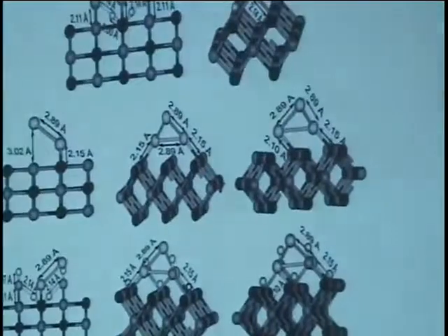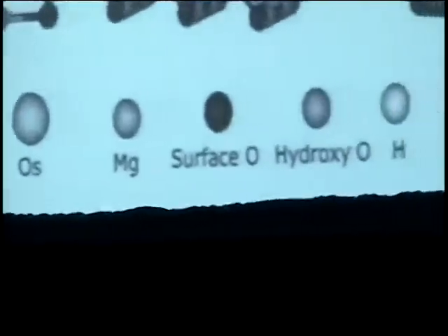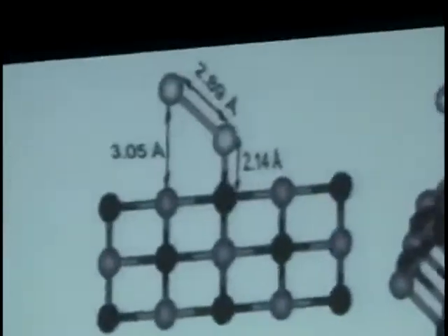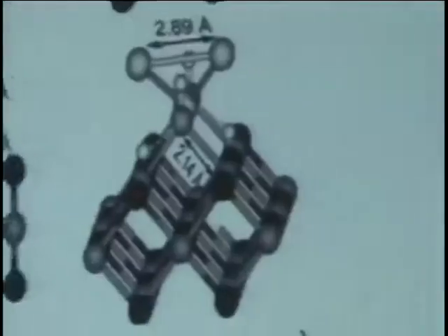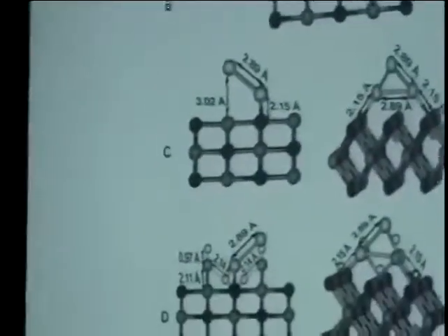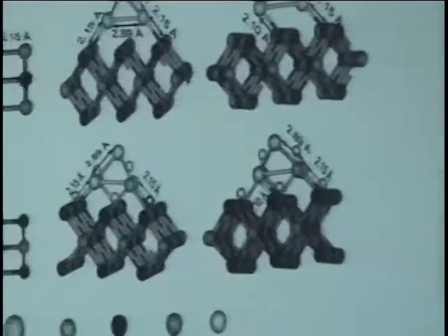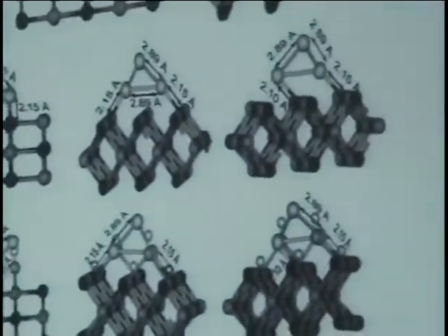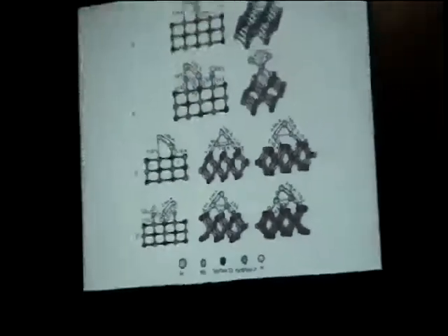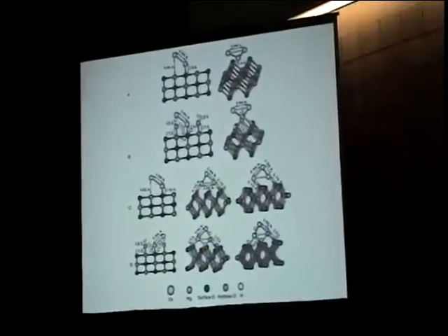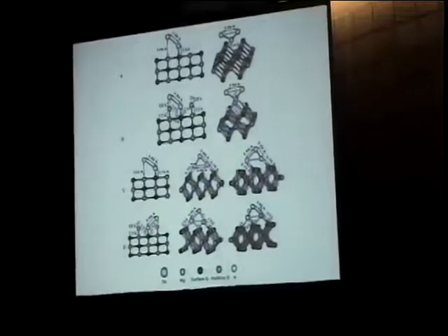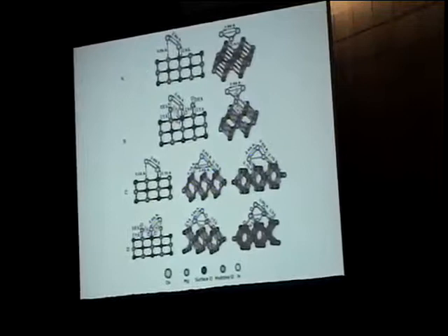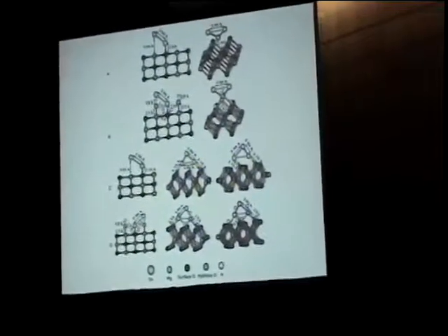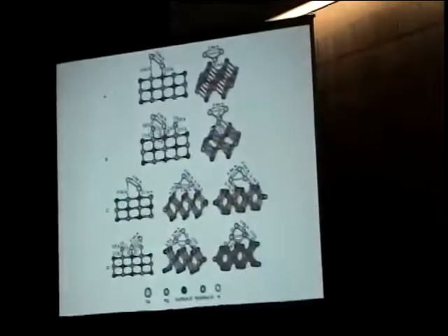So the structural models, the student did all the geometry. Thank goodness the student did it and I didn't. Figured with this face of MgO, with it hydroxylated or non-hydroxylated, placing it with the osmium-osmium distance matching the experimental value, and the triangles you saw were isosceles, so they're not planar, they're not perpendicular to the beam. So it becomes a geometry problem, but one can figure out that the only way the osmiums are atop the magnesiums is if the clusters are tilted with respect to the plane perpendicular to the beam, and the tilt angle turns out to be 38 degrees.